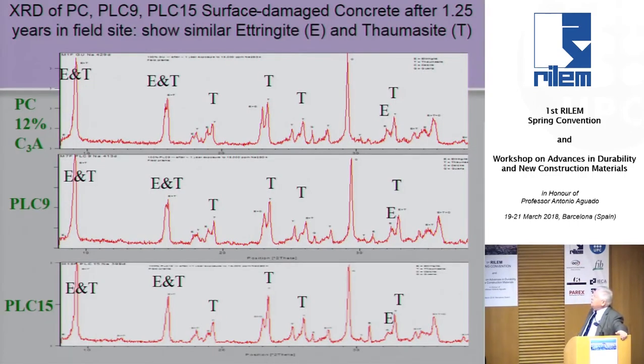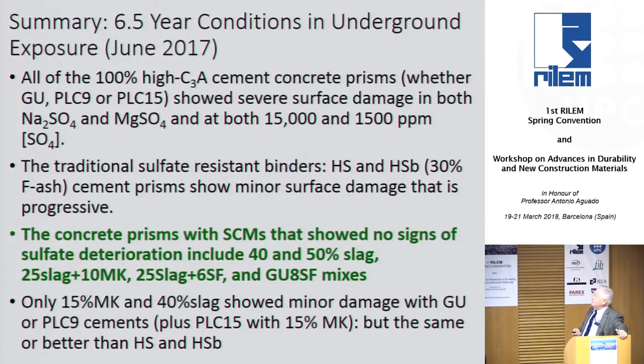And we did some work a little bit after. This is some cements, and what they have. The top here, we have a high C3A cement. We have the same clinker with 9% ground limestone, one with 15% ground limestone. And this is the surface damage after 1.25 years in the field site, where it varies between about 3 degrees and 15 degrees Celsius during the year. And we see, regardless of the limestone, even if there's no limestone in the cement, we're seeing exactly the same thing. We see some evidence of thaumasite and ettringite, but there's no difference with the limestone content. So it wasn't influencing the result.